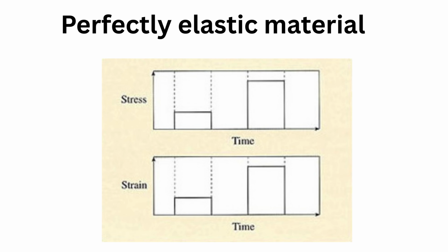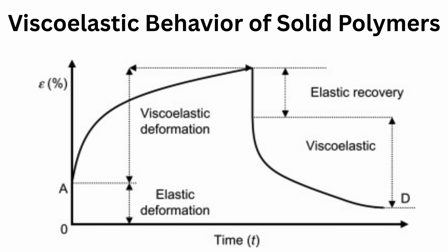When the stresses are removed from a polymeric material before fracture, the strain recovery path is not necessarily identical to that of the loading part of the deformation cycle. So energy must have been dissipated during the deformation of such materials, another indication of deviation from perfect elasticity. Both the deformation and the subsequent recovery are time-dependent, suggesting that some part of their behavior is viscous. In fact, solid polymers show a combination of elastic and viscous behavior known as viscoelasticity. The degree of viscoelasticity is strongly dependent upon the temperature of test and the rate at which the polymer is deformed, as well as such structural variables as degree of crystallinity, cross-linking, and molecular mass.